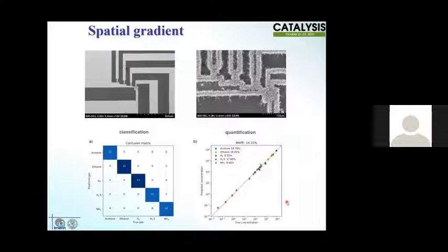The last, and in my opinion the best way, is to use not a temporal thermal gradient but a spatial thermal gradient. Basically, you see here a heater and in this case only four sensors placed at different distances from the heater.